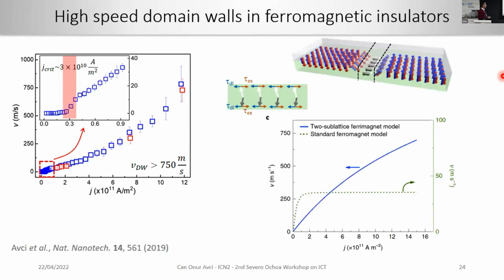And this is enabled by the ferrimagnetic nature of the materials, because you have these two lattices that couple anti-parallel to each other. So now I'm just considering the iron lattices that are anti-parallel. So you have these two magnetic lattices. The damping-like torque tries to tilt these two magnetic lattices towards the torque direction. However, the exchange interaction is so strong that it restores this damping-like torque effect. Therefore, the domain wall doesn't change its orientation, so it just remains as a Néel type domain wall, even though you inject a very high current density.